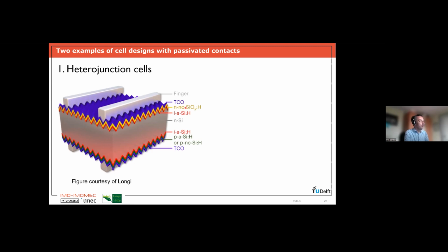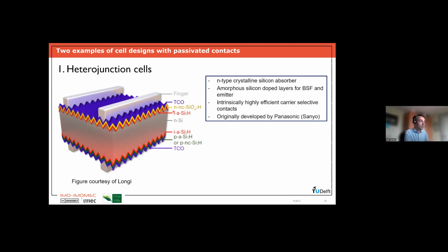And this is an example of a passivated contact because there is nowhere any direct contact between the metal on the front or the rear and the silicon. We always have these amorphous silicon layers and the TCO in between. So yeah, this summarizes what I was already saying before. So this is an example of passivated contacts and carrier selective contacts. It was originally developed by a Japanese company, Sanyo, that was later taken over by Panasonic.